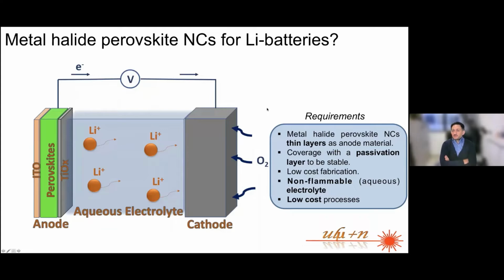So how are these materials suitable for energy storage applications, and especially for lithium batteries? This is the question we had about three years ago. So we considered a perovskite-based anode for lithium-ion batteries. You can see here the architecture of the cell. We have indium tin oxide as the conductive electrode, with the perovskite layer on top of this electrode to be used as an anode. And then we have the aqueous electrolyte.